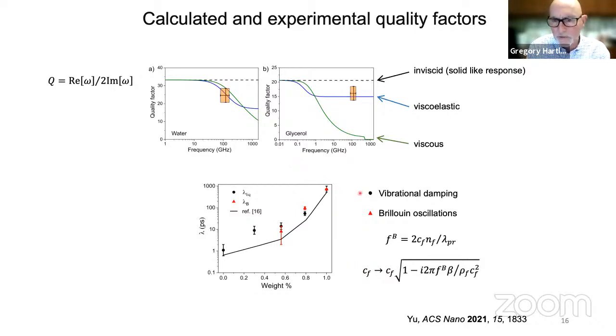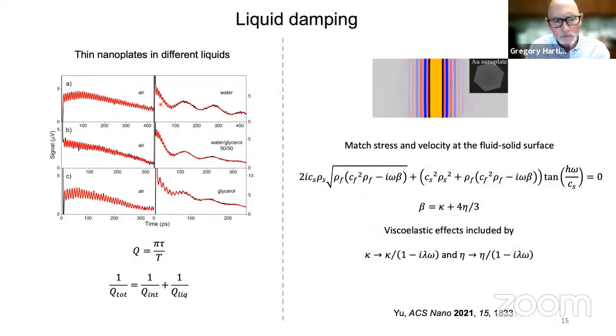And I forgot to mention those. I'm sorry, I'll go back. You see these long oscillations here? Okay. These long time oscillations are what we call Brillouin oscillations. When you have a metal nanostructure in a liquid and you hit it with a laser pulse, it will generate sound waves in the liquid. And the Brillouin oscillations are a reflection interference phenomenon from light that's reflected from the metal and from those sound waves. Okay, and the frequency depends on the speed of sound in the liquid, and also the refractive index and wavelength of the probe laser. Okay, so this is what these are.